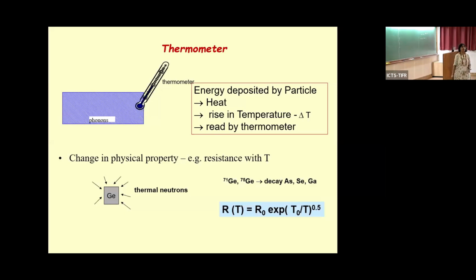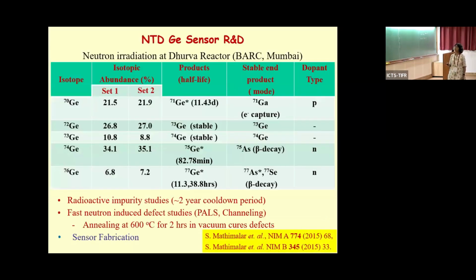Now, the first thing, when you want to make bolometer detectors, is I need a thermometer to measure the change. What we look at is some change in a physical property which varies with T. So what we chose was the neutron transmutation doped germanium sensor. Here the resistance R changes with T, as given here, and it is exponential, so it is ultra sensitive. So you take natural germanium and irradiate it with thermal neutrons, and given the natural abundances of the different isotopes, you make the products, and after the final decay you get a final doping into the system. Since this is the dominant one, you get mostly N-type doping.